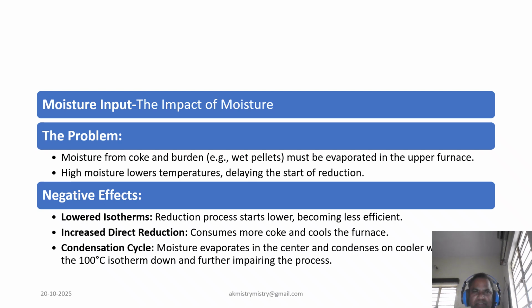The consequences: the reduction zone is pushed lower into the furnace, making it less efficient. This forces more direct reduction to occur, which consumes an excessive amount of costly coke and cools the furnace. Worst of all, it can trigger a vicious condensation cycle where moisture evaporates in the center only to condense on the cooler walls, driving the process further out of balance.